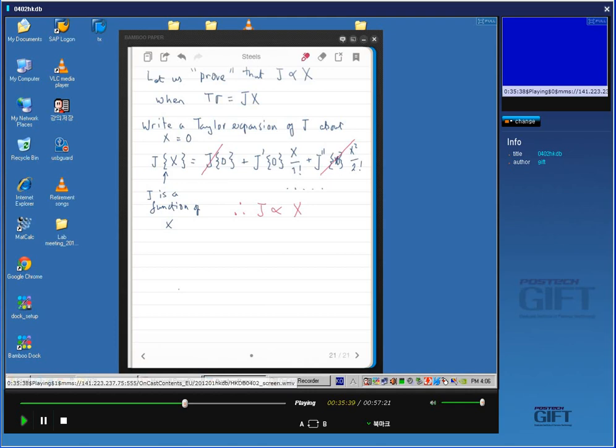Right, so what does this mean for Ohm's law, for Fick's law, Fourier's law? This is quite straightforward, the deletion of the first term. But what does this mean when we delete the higher order terms? What should you expect if I make the voltage difference extremely large? It may not be the case that the current will be proportional to the voltage. It's very difficult or even maybe impossible to do such an experiment, because as soon as you apply a very large voltage difference, you get a lot of heat generated. But in the case of diffusion, we can actually apply very large gradients of concentration by depositing, for example, one layer of gold on top of one layer of silver. That's the biggest gradient that you could get, right?